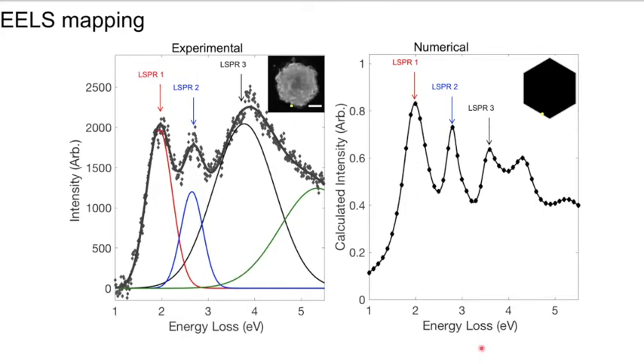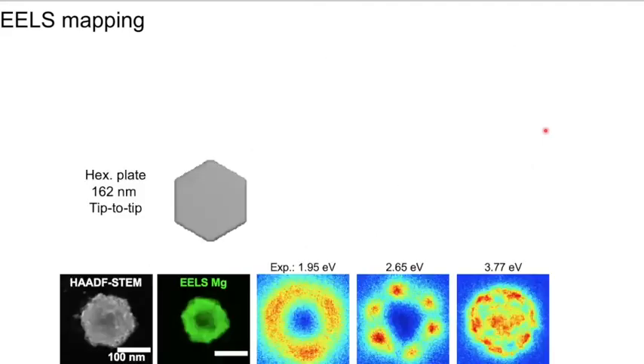of various energy. We can map this to our numerical result. It only works if we get all of the parameters in the numerics right. We must put an oxide on the surface of the particle because that shifts the energy of the plasmon resonance. We must put a substrate because that also shifts the energy. But once we do that, we get a really pretty good match with our experiment. And you'll see in a minute that that's really key to understanding what's going on in these particles.